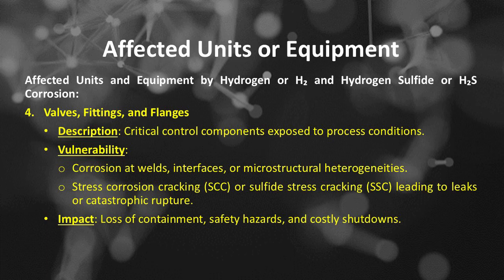The vulnerability of high-temperature hydrogen (H2) and hydrogen sulfide (H2S) corrosion to the valves, fittings, and flanges includes localized attack at sealing surfaces, threads, and joints, pitting and crevice corrosion under gasket or bolted assemblies, embrittlement and cracking under high-stress and corrosive environment. The impact to the valves, fittings, and flanges: leakage, operational failures, and maintenance challenges.